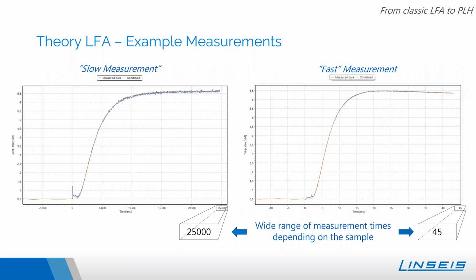Some samples are really thick and slow, and the measurement times are really long, like 25,000 milliseconds, which is 25 seconds. This is for a sample in the polymer range that is really thick. Otherwise, your sample can be really thin and metallic, a highly conducting material, and then your measurement times are really short, like 45 milliseconds. As you can see, it really depends on the sample how long the measurement will take, and how long it takes till the half-time rise, till the temperature rise is completed.